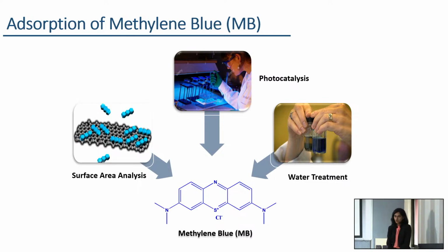Here, due to the presence of oxygen functionalities and the pi-bond conjugated structure, these GO based materials have a strong affinity for methylene blue. Therefore, methylene blue adsorption onto these materials is highly dependent on the structural features of GO and RGO. So, in this study, I have used the methylene blue dye molecule as a model molecule to probe these structural variations of graphene oxide and reduced graphene oxide during their synthesis. This is the first time that methylene blue has been used as a probing molecule to analyze these structural variations of GO and RGO.